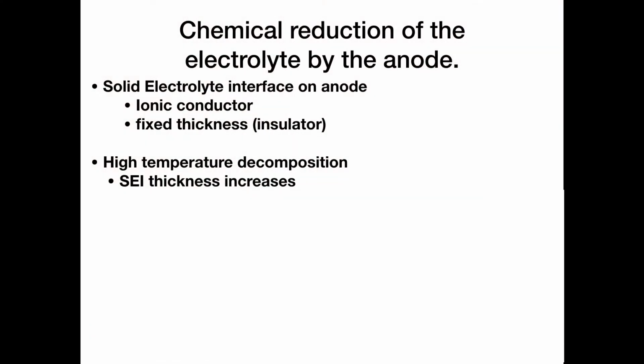What is interesting about it is, once it occurs on the initial level under initial conditions, at kind of standard run-of-the-mill atmospheric pressure and temperatures, the film thickness is pretty constant. It acts as an insulator to keep this from growing, and it works. It doesn't get any thicker, it doesn't get any thinner, and it allows for the perfect rate of transfer of these electrons. What can happen with that is the thermal decomposition. We've got some real issues that if we raise the temperature, if it gets too hot, the reaction rate increases. And so we end up increasing the thickness of our SEI layer.